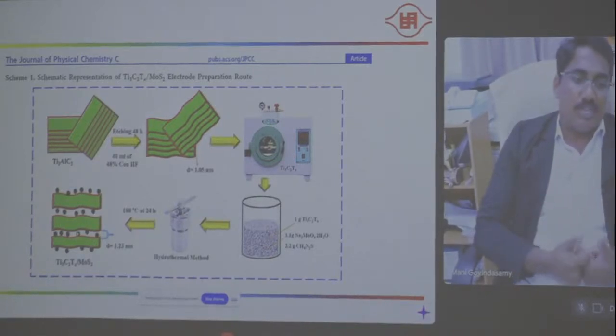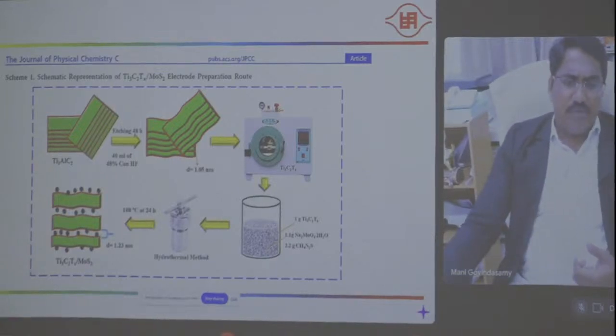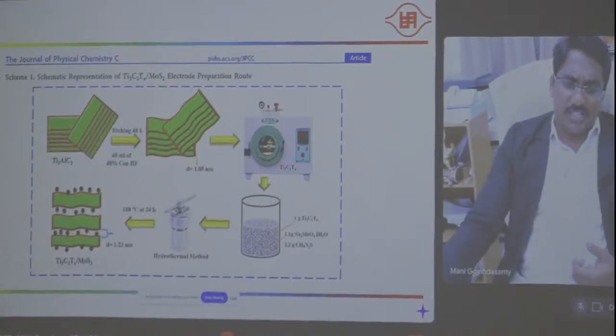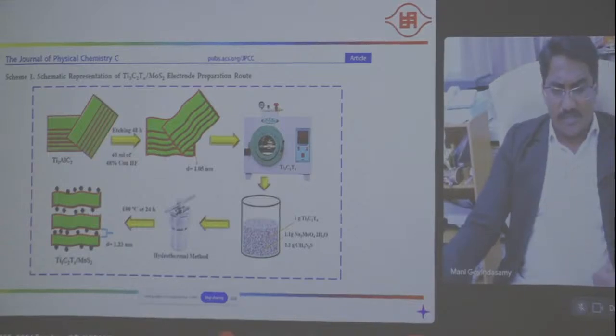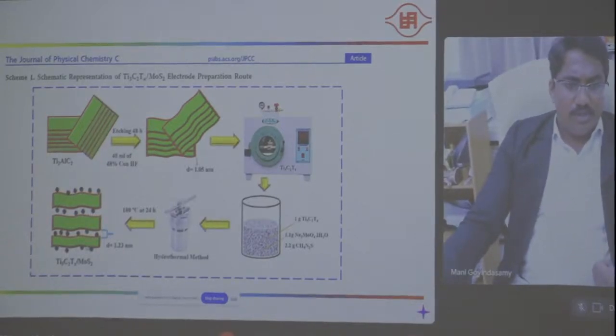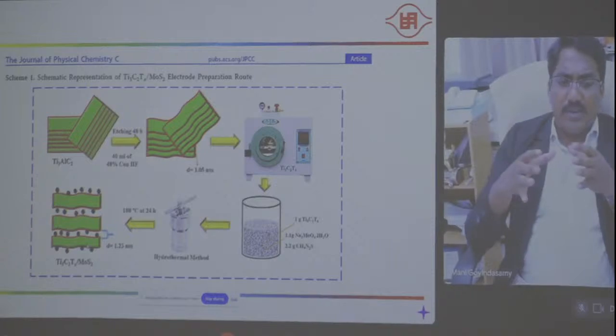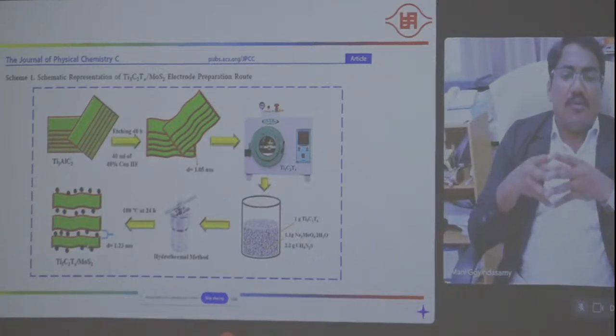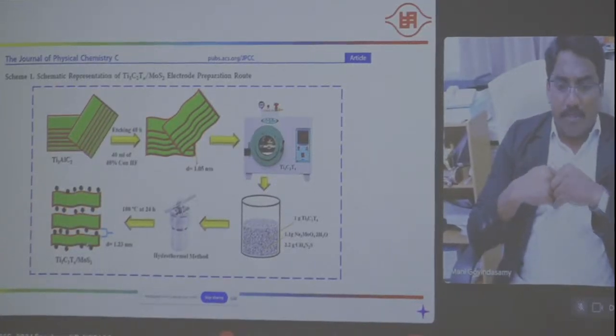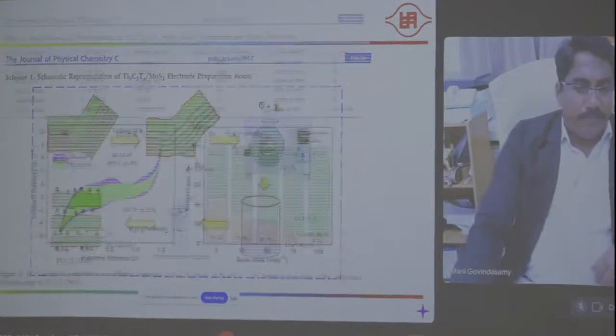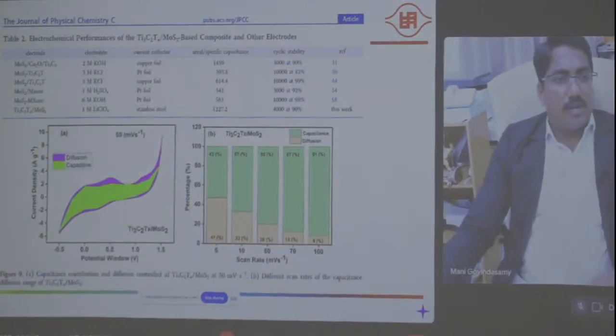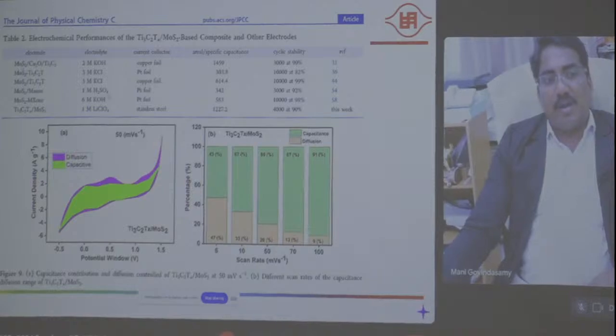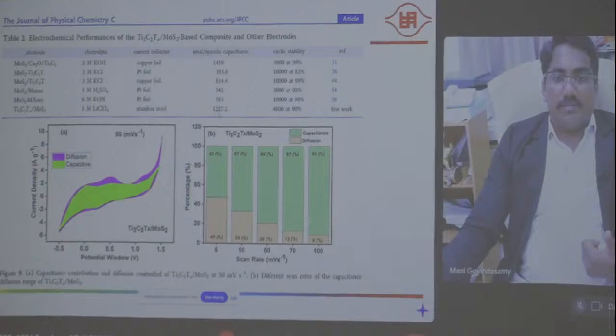structure of composites. In this work we got the molybdenum sulfide also in a sheet-like structure, as well as the MXene also a sheet-like structure. Both composites, for example bi-layer sheets, have higher electrochemical properties, particularly energy storage property. Compared to other previous molybdenum sulfide related materials, we developed around 1227 specific capacitance. Also the cyclic stability is better.